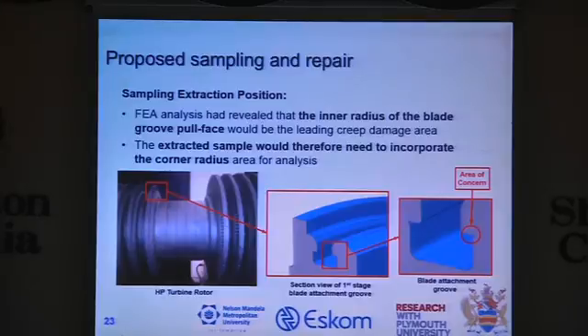For the sake of time, I'm going to go a bit quicker. In South Africa, 5 years ago, 10 turbines, end of life, had to be replaced. There's no way we can take 10 turbines out of service. The German manufacturer indicated the area of concern is on the pull face in that area, and all the models showed end of life, severe creep damage. And you have to believe this, unless you can show it is not the case.